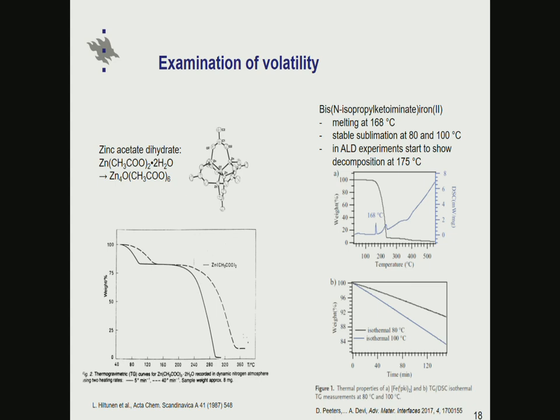So here is an old example of a precursor which eventually is completely evaporated, but there is a step in between. The starting compound here is zinc acetate dihydrate. What happens in the first step is that the water molecules are released, and there is also a reorganization of the ligands around the zinc atoms in the molecule. It forms a tetramer, which looks like that one. It's actually quite heavy, and as such not a very attractive ALD precursor, but anyhow, this can be volatilized once going to high enough temperature so that zero residue is left.